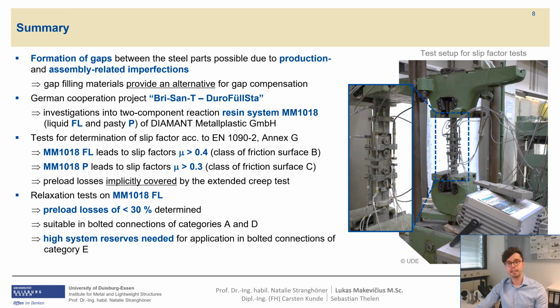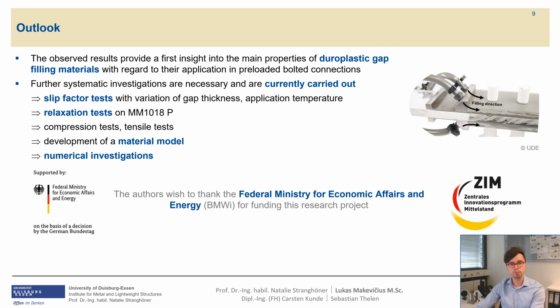This indicates that the application of the gap-filling materials might also be possible in preloaded tension connections of category E, as long as high system reserves due to tightening procedure can be ensured. The observed results provide an insight into the main properties of Duroplastic gap-filling materials with regards to their application in preloaded bolted connections. Further experimental investigations, including slip factor tests, relaxation tests, as well as compression tests and tensile tests, are currently carried out. Based on these test results, development of a material model, including numerical investigations, is intended.